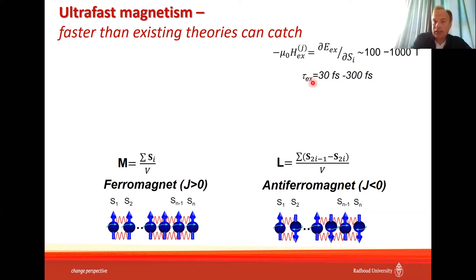then how do you calculate this period? You basically take the energy of the exchange interaction between the spins, the derivative of this energy with respect to spin, and calculate the effective magnetic field with which a spin acts on its neighbors. And this effective magnetic field, taking realistic energies of the exchange interaction, can be from 100 to 1,000 Tesla. So that's why magnetism is basically the strongest quantum mechanical phenomenon on Earth.